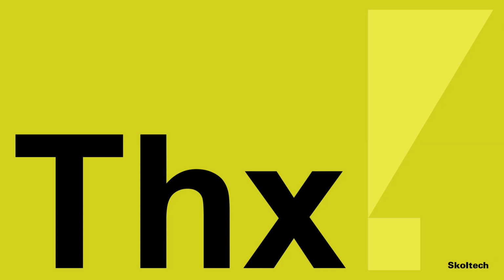Now, in our case here, the reason also we demonstrate that within a picosecond we can switch on and off is that we can pump with a femtosecond pulse. So we send a femtosecond pulse, and that creates one bit. Now, the condensate appears, and then it disappears within few picoseconds. So instead of pumping continuously, we pump with femtosecond pulses, but the clock rate is the rate of the pulses. So we can go to several megahertz, maybe we can drive it to gigahertz. With different materials, with inorganic structure, we could definitely go to tens of gigahertz.